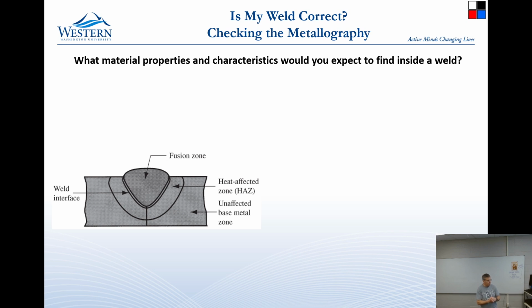And then they came out on site and they did all of the welding in tents where they were protected from the environment. And then every 5th weld got full radiography where they used x-rays to look for any cracks that were in it. Every weld they coated with dye to see if there were any cracks that showed up. You put dye in it and then you use an ultraviolet light to look at it. And then about every, can't remember if it was every 20th or every 50th weld, they actually made the weld, cut it out of the pipe, and then sent it away and did destructive testing on it to see if it was good enough.